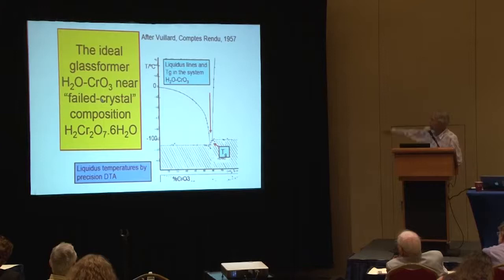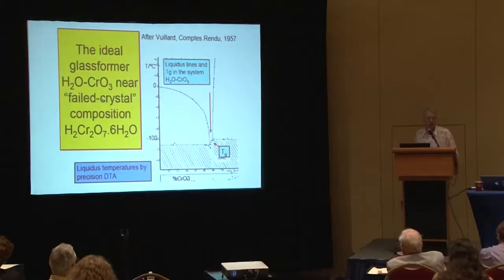Well, here's one case that I dug up long, long ago from the French literature, the case of dichromic acid, where the melting point of ice is depressed down there, and the melting point of the next crystal is the same, and in this middle part here, all you see is a glass transition. So it goes into the glassy state in the thermodynamically stable condition, and that would then be impossible to crystallize. We actually use this system in experiments later on. I just want you to be aware of that possibility, which gives another break from my voice.